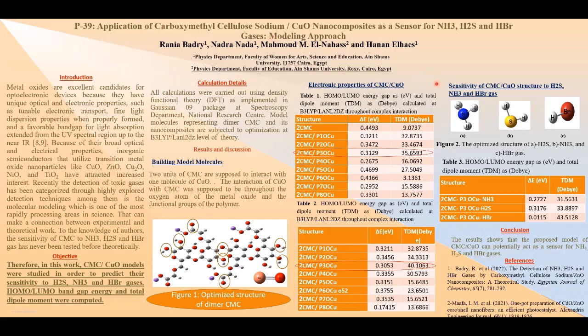Additionally, the sensitivity of the proposed structures of CMC and copper oxide to the H2S, NH3, and HBr gases is also studied in terms of the total dipole moment and HOMO-LUMO band gap energy, as presented in Table 3, as the reactivity of the different structures is closely related to the band gap energy between their HOMO and LUMO orbitals. At that point, the higher the reactivity, the smaller the band gap and the lower the stability, and the higher the total dipole moment.